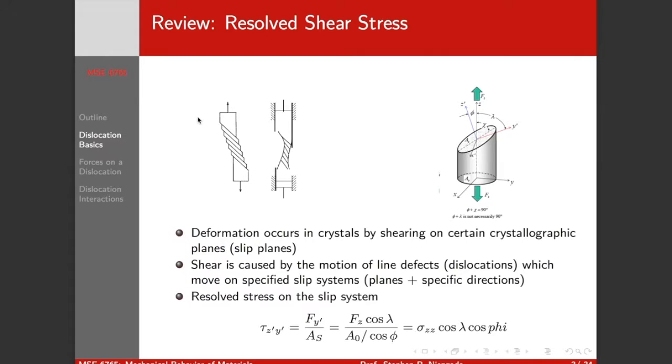But if we think about a defect moving on this plane, we need to know what is the shear, what is the force acting on that dislocation. So we introduced this concept called the resolved shear stress. And that is the stress projected onto the slip plane.